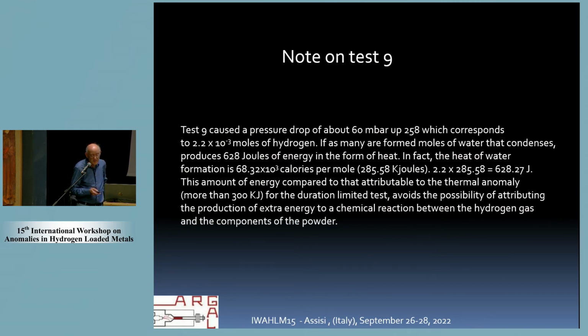There is a note about test 9, because it was done after the oxidation of the material. Then we charged the hydrogen, removing the air used for oxidation. During the test, there was absorption, but also consumption of hydrogen due to the reduction reaction with oxygen remaining in the powder. But if you see here, the calculation of hydrogen consumed by the reduction of pressure accounts for only a small energy respect to what is produced by the extra heat.